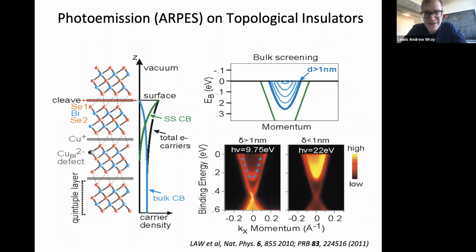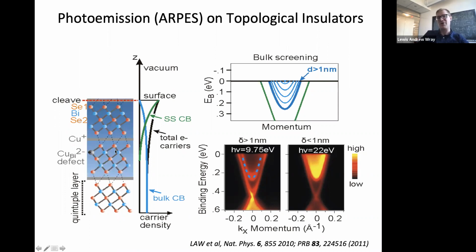Anyway, getting into practicalities. When we study a material, like bismuth selenide, a classic topological insulator with an electronic structure that looks like what I was just showing, we take a chunk of the material and put it into ultra high vacuum, and then we knock off the surface of the material. So we knock off a piece of the top and get a new surface that's cleaved, that has never seen air, that's ideally perfectly clean. The surface electrons tend to live in the top layer or so, and bulk electrons are sort of everywhere. Then we shine light on it and knock electrons out and measure the energies and momenta of the electrons outside to reconstruct the energy states they were inside the material.